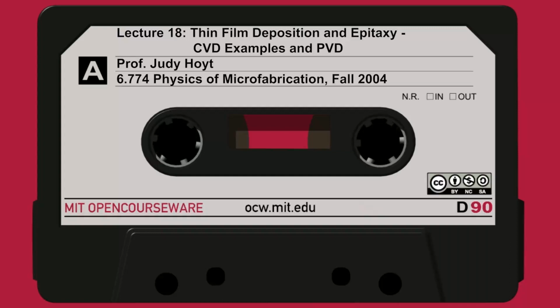So as a function of L over H, you see the depth rate can be calculated just according to these two equations. So when L equals H here, you can calculate the relative depth rate compared to the depth rate directly perpendicular from the source. It's down by about 30% of what it would be right at this point. So you get an idea of what the uniformity will be along this surface. And there's different curves. The dashed line here is for the surface source, and the point source is the solid line. So they have slightly different dependence on those parameters.